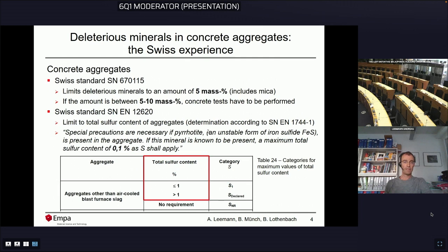Now, about iron sulfide. Swiss standard SN EN 12620. There are limits given there to total sulfur content of the aggregates, and how this sulfur content is determined is defined in another standard, the SN EN 1744-1. And if you look at the table at the bottom, you see there the total sulfur content. There are in principle 3 categories. If your total sulfur content is below 1, it's S1. If it's above, it has to be declared, and there's a class with no requirement. And it is stated that special precautions are necessary if pyrrhotite is present in the aggregate. If this mineral is known to be present, the maximum total sulfur content of 0.1% as sulfur shall apply. Next, please.